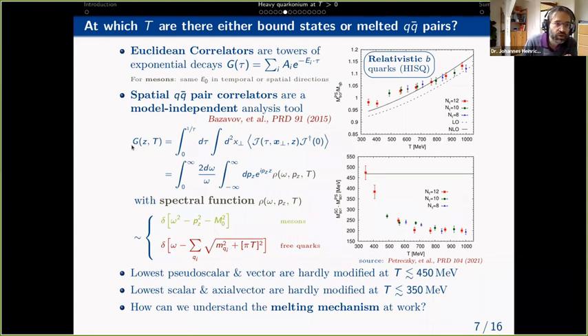And so what we can do is compute a correlation function at fixed temperature in the z direction of the lattice. In this case, that is an operator that we just have to implement and then measure, and this is related in a somewhat complicated form to the finite momentum spectral function on the lattice. As long as we have genuine mesons, we know that the lowest feature is a bound state peak, so it's a delta function at the meson mass, and as long as this meson is essentially the same as at zero temperature, we'll get essentially the same energy in the large z decay of our correlation function.